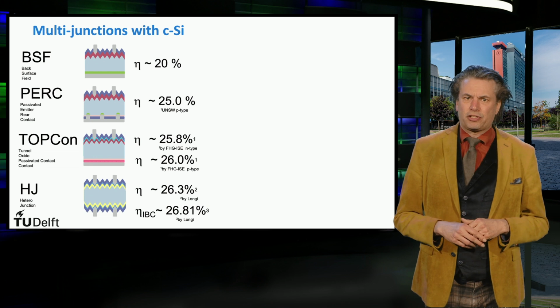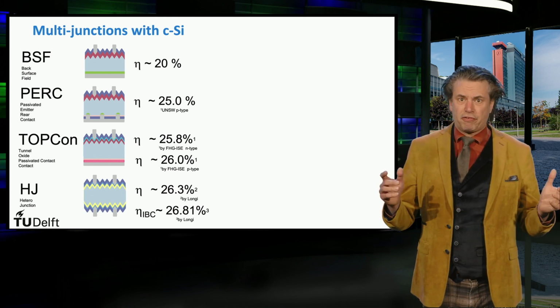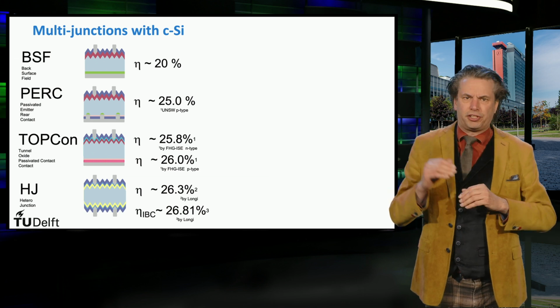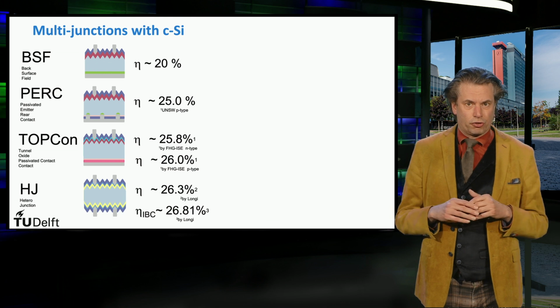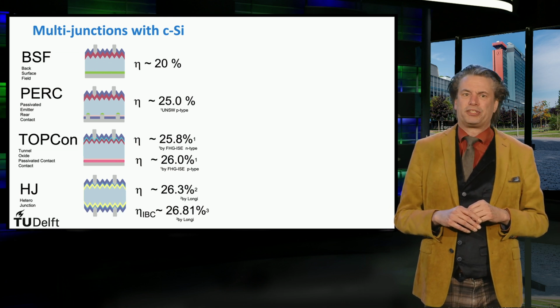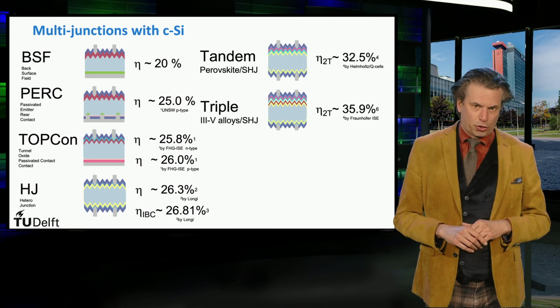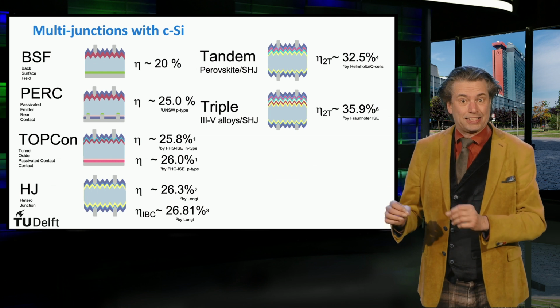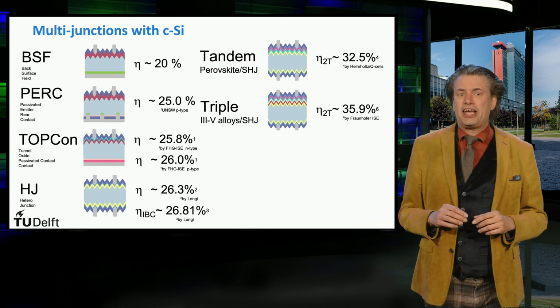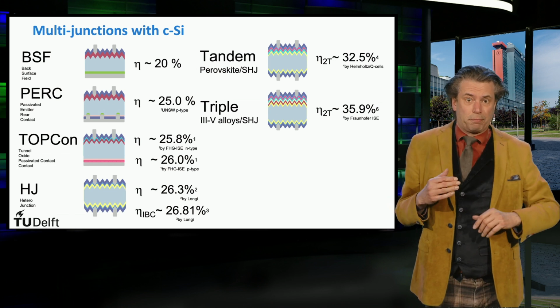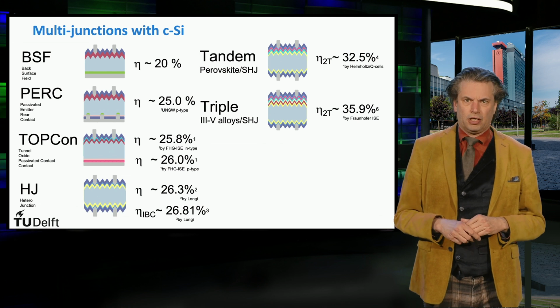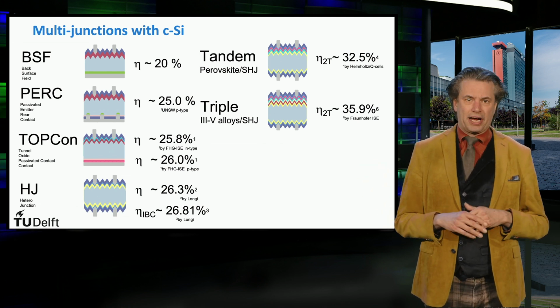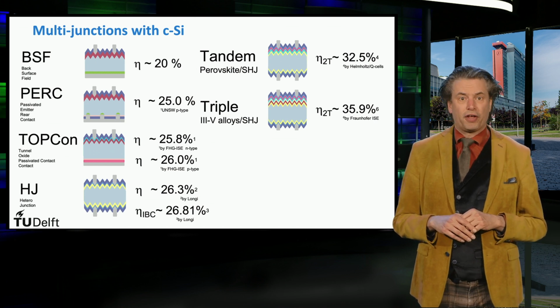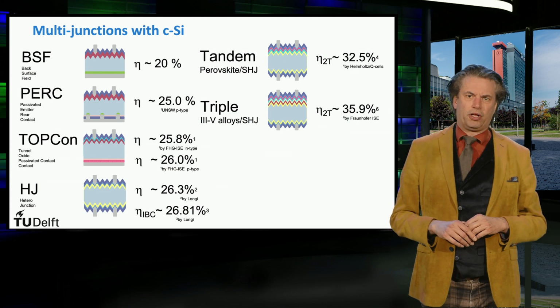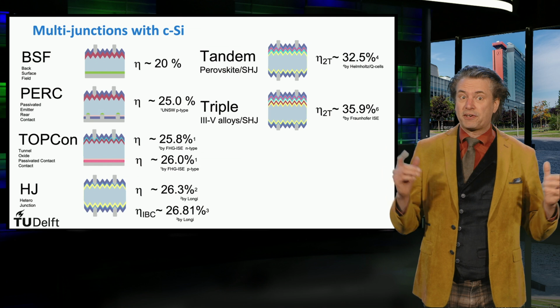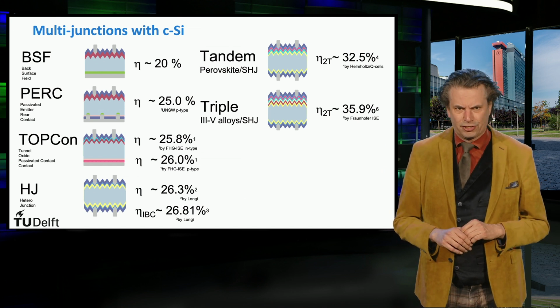The crystalline silicon PV technology dominates the commercial PV market. However, the record efficiencies shown here start to approach the theoretical limit of the conversion efficiency for a crystalline silicon solar cell, which equals 29.4%. For that reason, new hybrid multi-junction concepts are being developed with crystalline silicon as bottom cell. One architecture under study is a tandem cell with a high bandgap perovskite based top cell and a crystalline silicon bottom cell. The current record conversion efficiency has been achieved by Helmholtz and Q Cells with a conversion efficiency of 32.5% for a 2-terminal architecture, which is higher than the 29.4% theoretical limit of a single junction crystalline silicon cell.